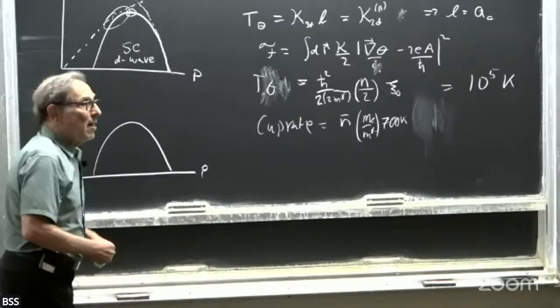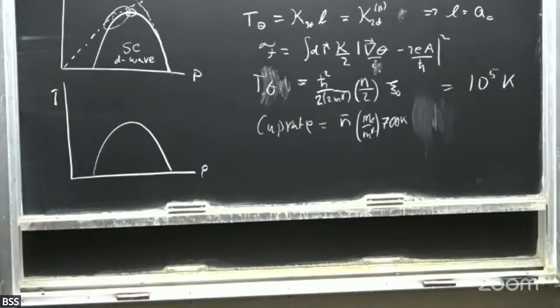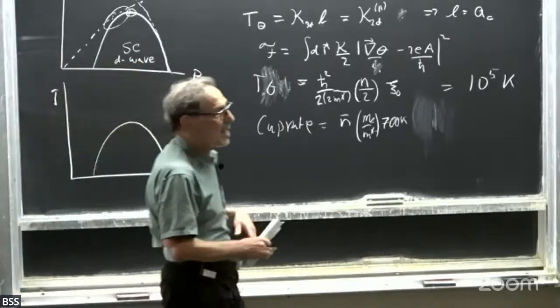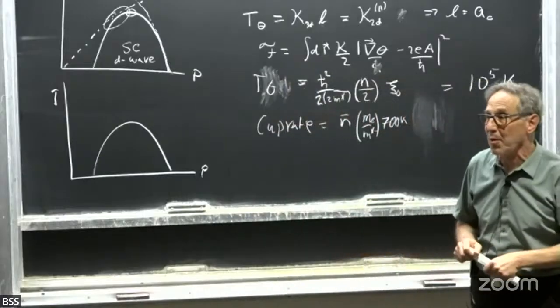So the advantage of this is you can look at the gap near the node. And so superconductors have a nodal gap right at the Fermi energy, and nothing else sensible does. So I think there's every reason to believe that the gap you see opening up on the Fermi surface in the neighborhood of the node is the superconducting gap without any ambiguity. And then one can turn that into a number, say, fit that to a cosine kx minus cosine ky form and ask what its amplitude is.